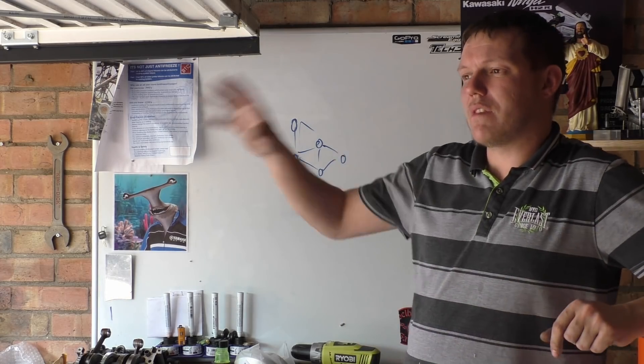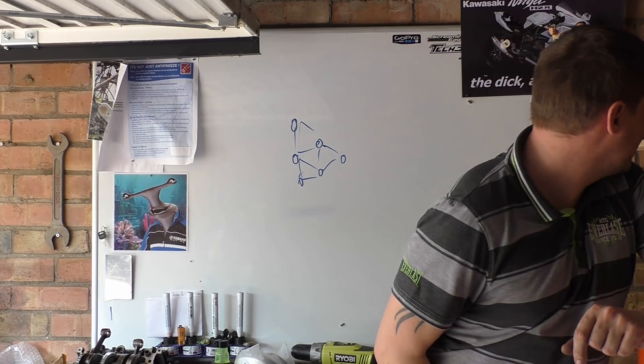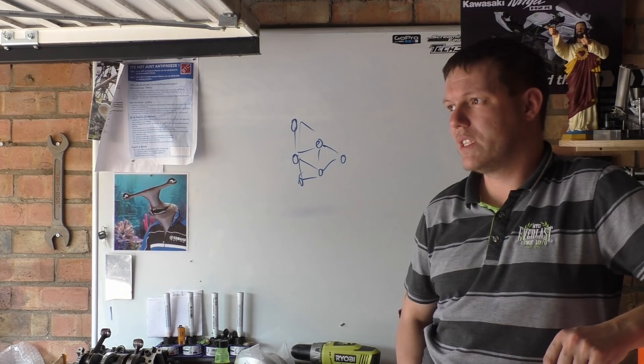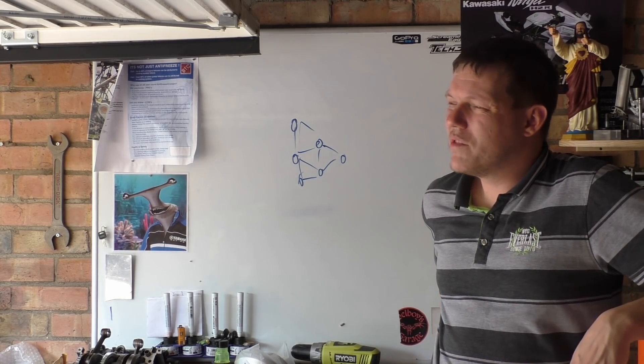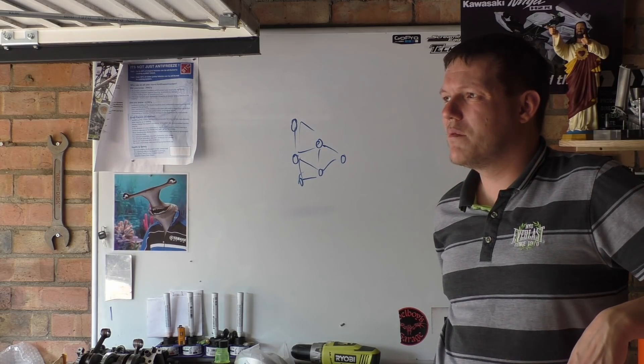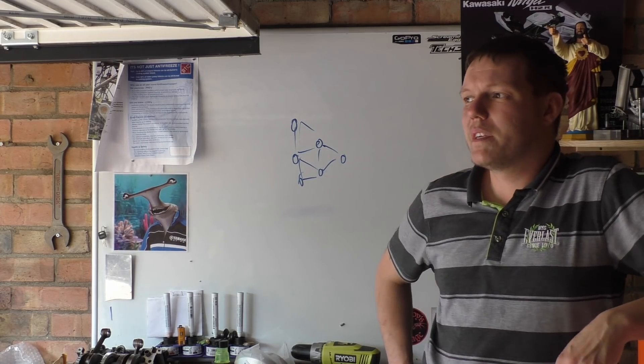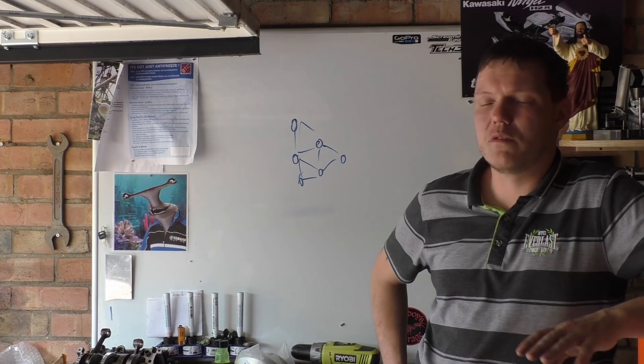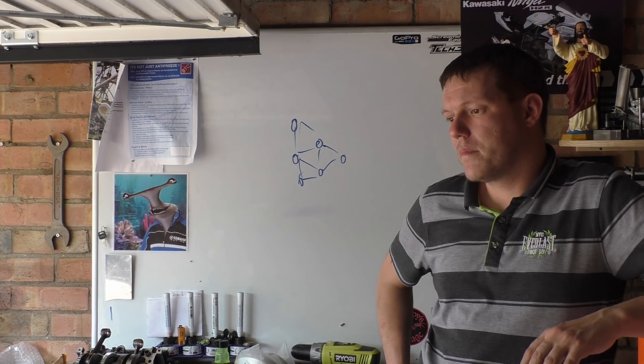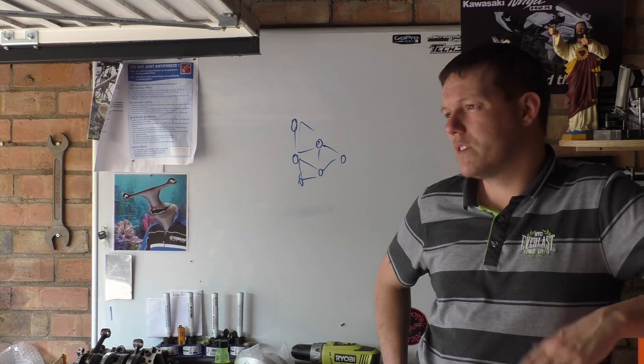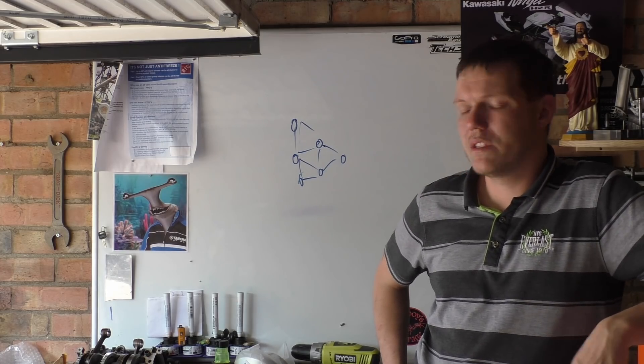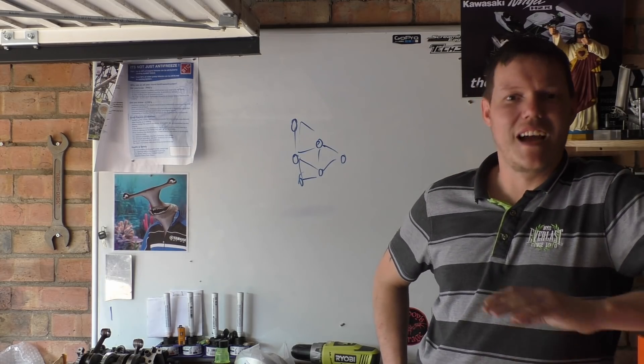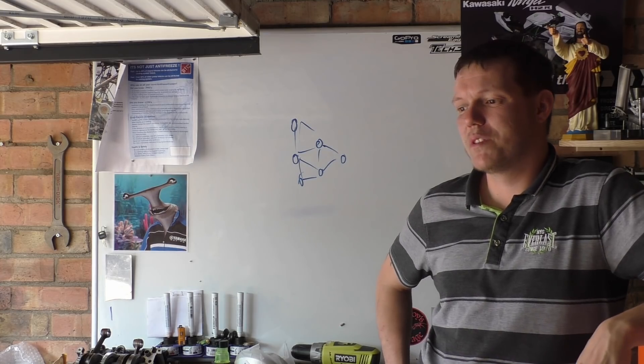For engine components, people just think ceramics and heat. But they don't make turbine blades out of ceramics because they would shatter — they'd be terrible. They've got okay creep resistance, and we'll go into what that means. It's also the way they fracture that's the problem. Ceramics are generally quite porous as well, which doesn't help crack propagation. But yeah, ceramics are good for heat insulation — that's about it when it comes to engines. We don't really want to use them for anything else.